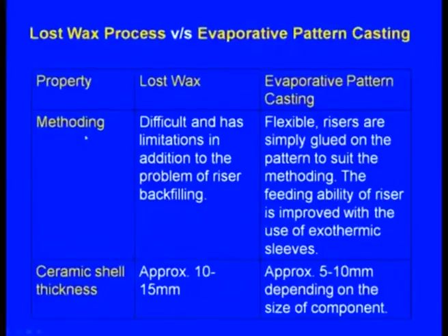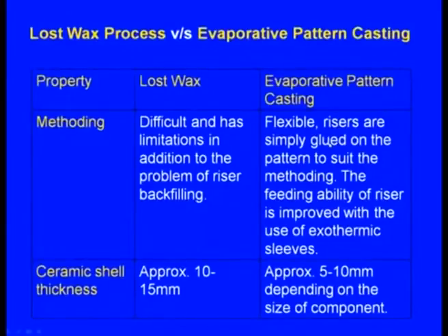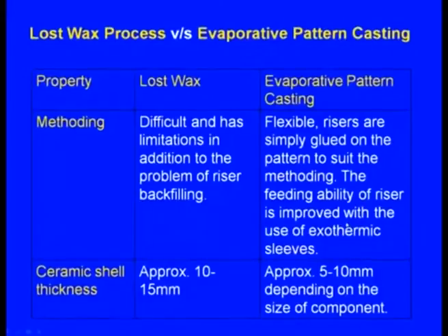Next one, methoding. In the case of the lost wax process, it is difficult and has limitations, in addition to the problem of riser backfilling. In the case of the evaporative pattern casting, flexible risers are simply glued on the pattern to suit the methoding. The feeding ability of the riser is improved with the use of exothermic sleeves.